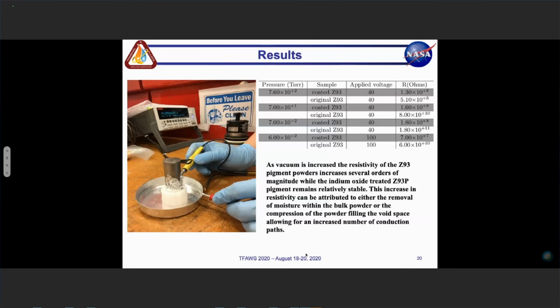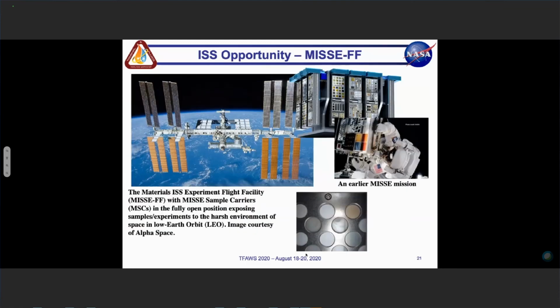resistivity that you're seeing from 10 to the plus 2 to 10 to the minus 2, much of it is your outgassing of water, which is a huge concern when it comes to some of these powdered resistivity measurements. With this high vacuum, we're actually able to remove moisture content within the bulk powders. So as we go to much higher vacuum, we get a much more accurate result of your resistivity.